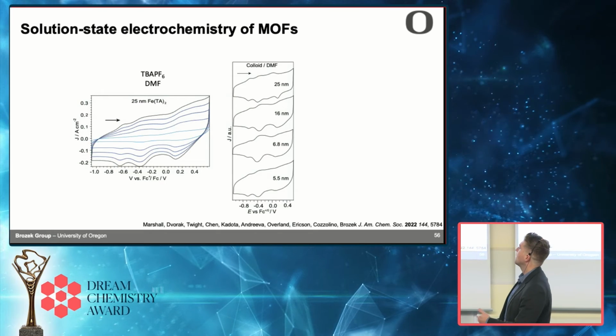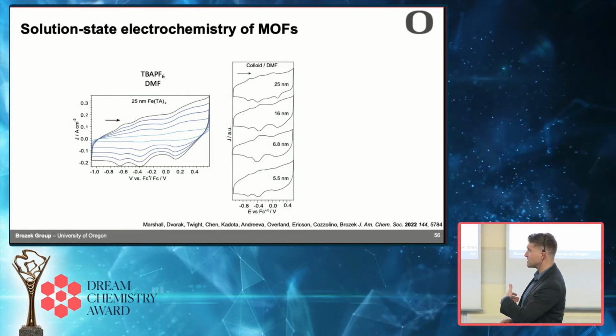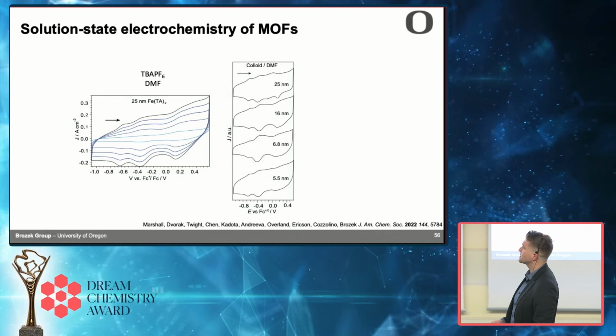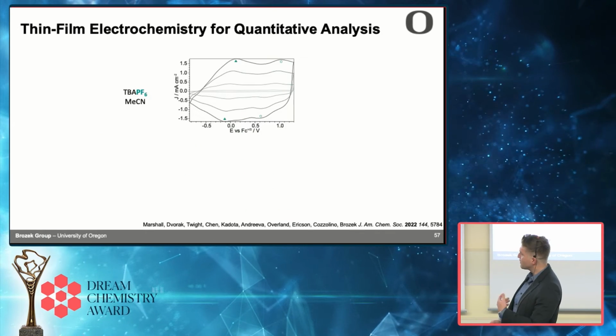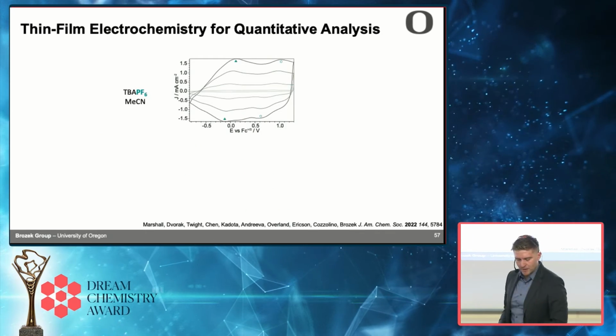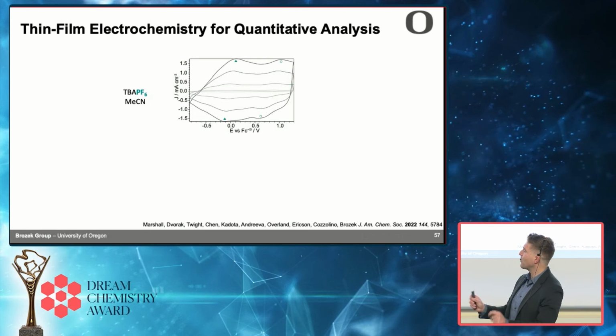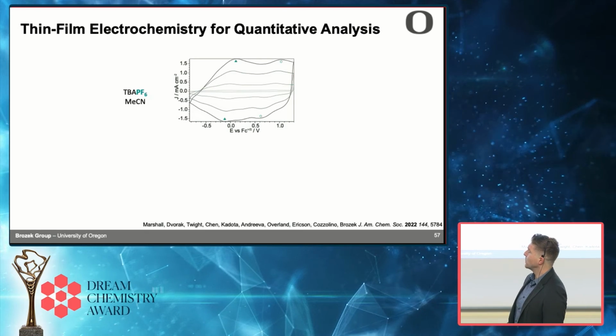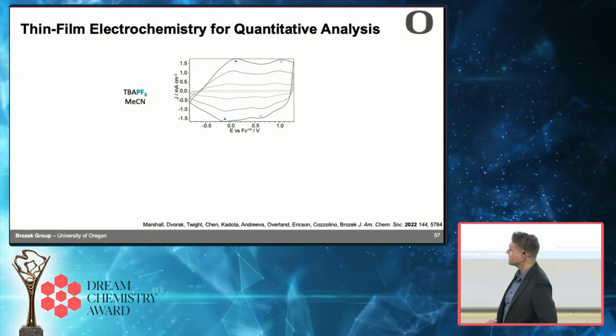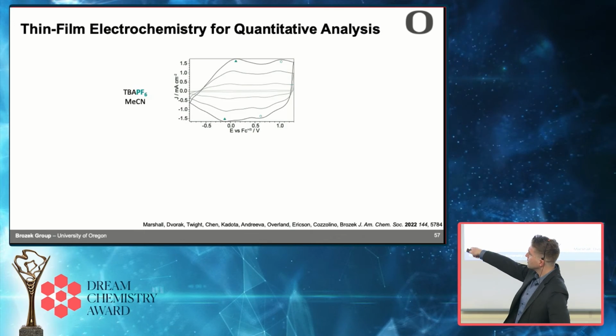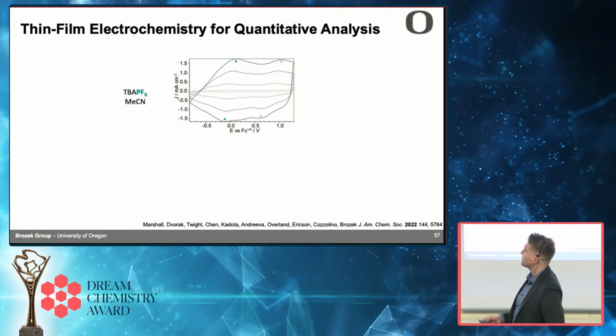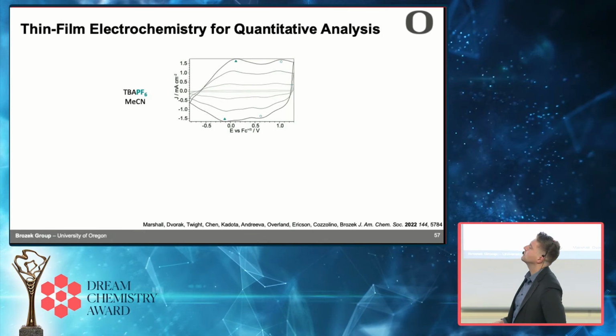It's unexpected. And we wanted to understand what was going on here, so for more quantitative insight, we took advantage of the fact that we can make them as thin films. And so we cast them as thin films on an electrode. We repeated the measurement, this time in acetonitrile so that the particles don't dissolve. We see a CV trace that's qualitatively similar, multiple quasi-reversible waves separated by half a volt or so.